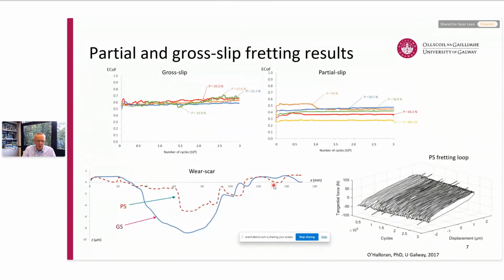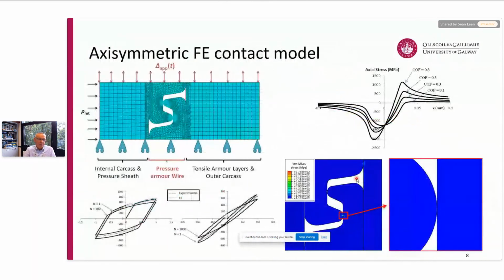Lots of challenges around that. I won't go through the details of that now. And then in the bottom right, you see typical what are called fretting loops, which show the force displacement, basically response, energy hysteresis response, if you like, and the kind of displacement that we've controlled down to about plus or minus 2 microns in this case. So that's showing some sample results from the experimental characterization. Then I'll talk a little bit about the modeling.